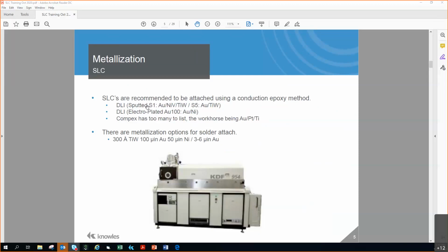And also Compex. Compex has a Ti-Plat gold. What they did years ago is they went to a tungsten platinum gold metal stack, and they did this because it could be either wire bond or solder. They didn't really have to change the metal stack. You can do either or on it.